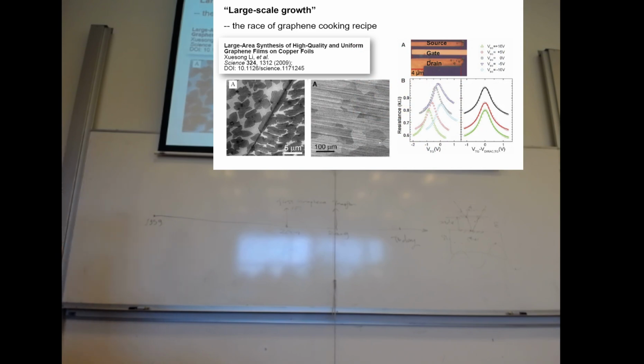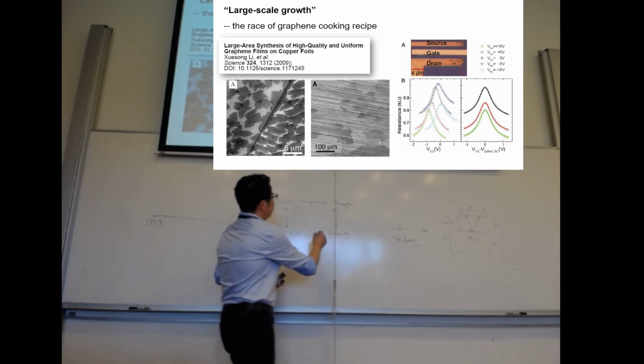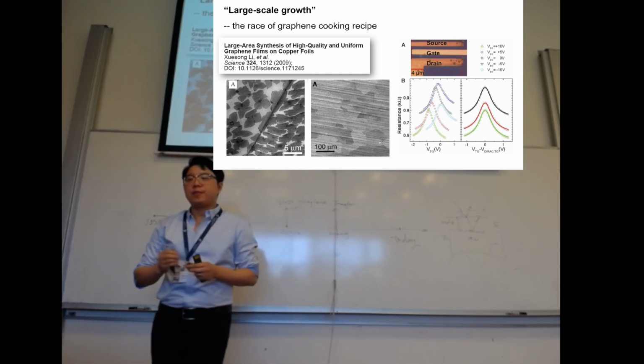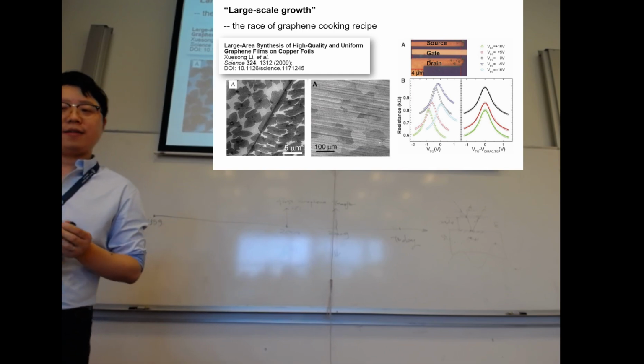Then there was also big progress in 2009. People found that actually using this transfer method, this is from, I think, also Professor Ruoff's group in 2009, they published a great paper in Science. So using this copper method, they obtained grains of a 2D material, which is carbon, which is graphene. And then if you grow for enough time, all these grains will merge into a single sheet, which is fully covered, 100% coverage of graphene. Then using this wet etching method, you can transfer this from copper to silicon oxide.